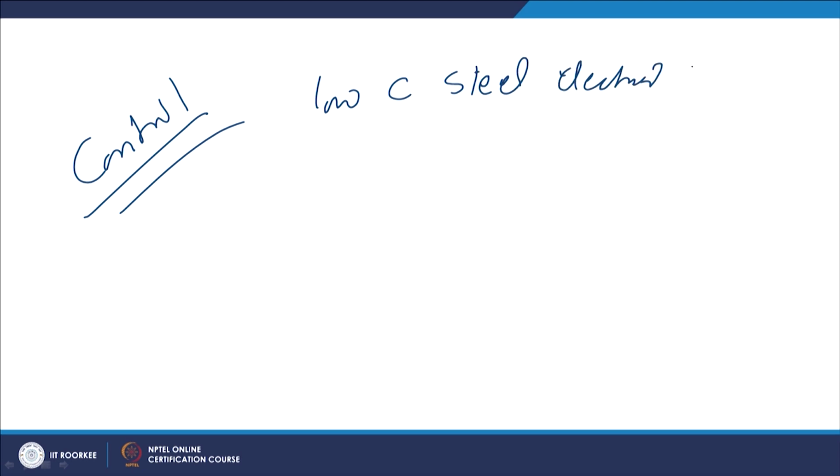So, our yield strength is less, which will reduce the tensile residual stresses, as well as ease out or make the weld metal more accommodative for the locked-in strains. If we take the low hydrogen electrodes, that will further reduce the tendency for the presence of hydrogen in